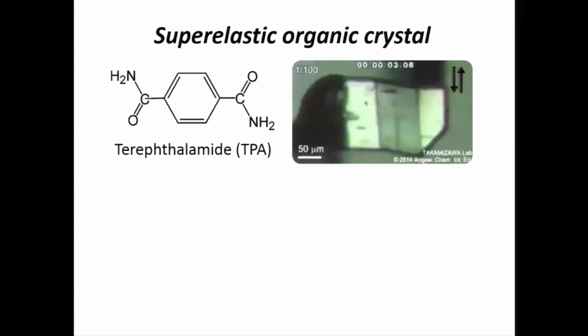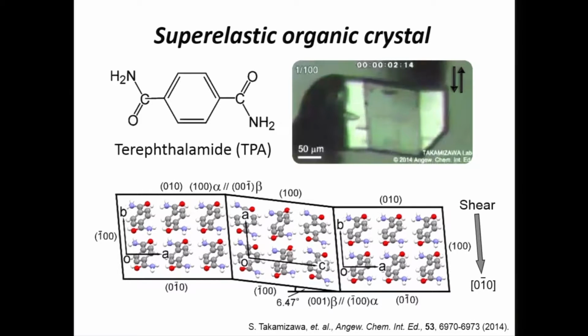And this new crystal domain has another crystal structure in this case. So this is shear-induced phase transition. And in this crystal, terephthalamide gathers to form an intermolecular hydrogen bonding network solid. And by analysis, you can find a very strict correlation in molecular orientation, change in molecular orientation, fitting of the crystal cell, and the shape of the crystal deformation.